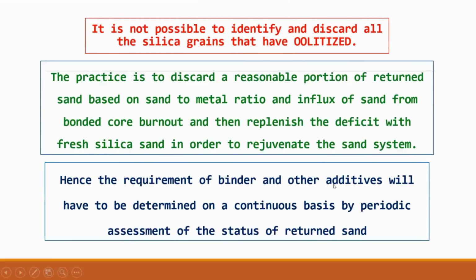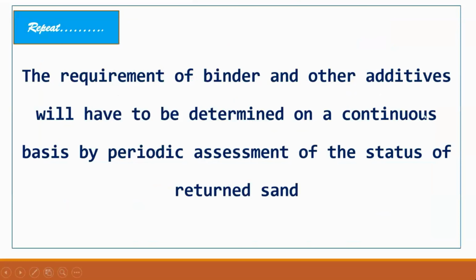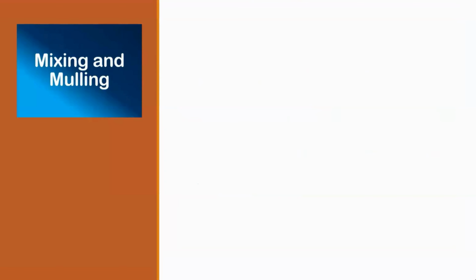Hence, the requirement of binder and other additives will have to be determined on a continuous basis by periodic assessment of the status of the return sand. Let's repeat it. The requirement of binder and additives will have to be determined on a continuous basis by periodic assessment of the status of return sand. So return sand analysis is the crux of the whole process, and that has to be done in a thoroughly mixed condition at ambient temperatures. Now, having done all this, we have to send this sand to the mixer. It's also called the muller.